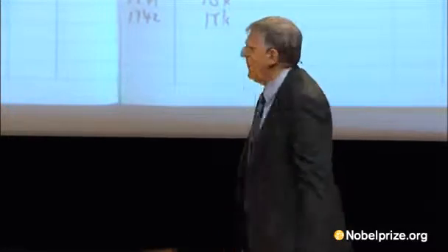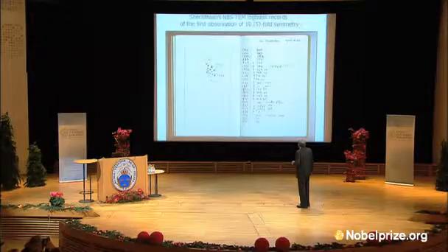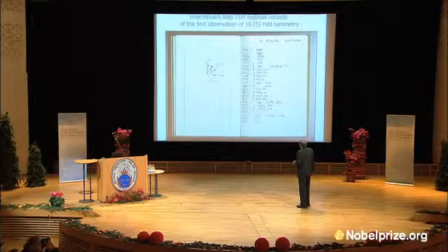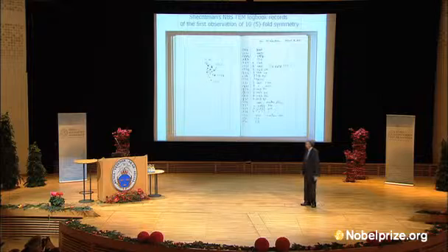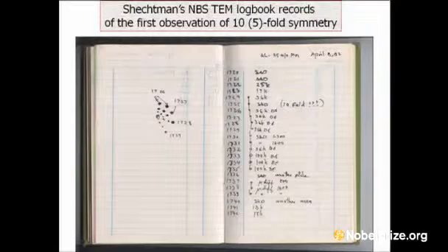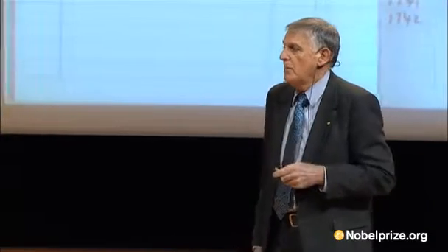Let's look at the diffraction pattern. And I look at the diffraction pattern, and I say, tenfold, and this is the diffraction pattern you saw before, and you will see it again. And then the question was, okay, I will go through whatever I did here because it seems to be a little bit important. Then I said, okay, tenfold. Later on, it turned out to be fivefold, but I could not find out by this method of diffraction that it was really fivefold. It has to be done by another experiment, which we did later on.